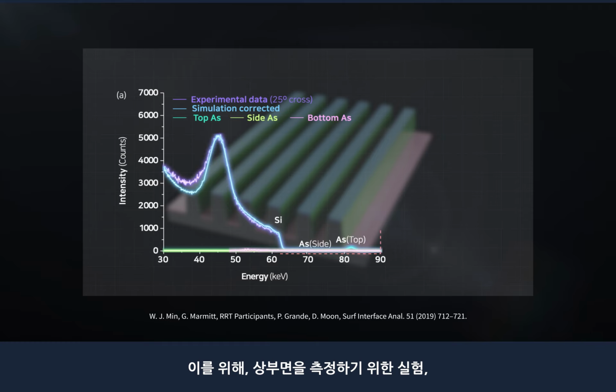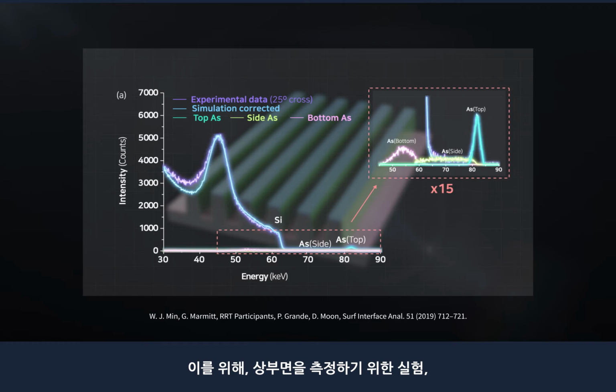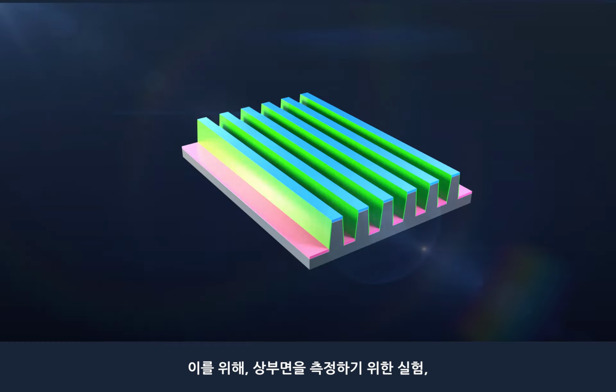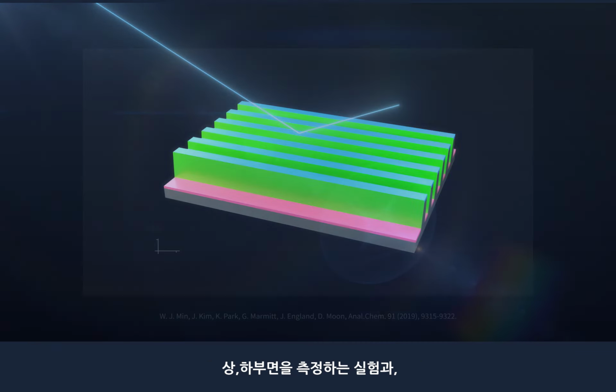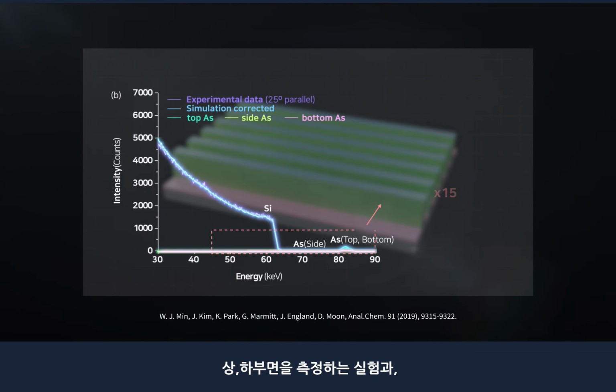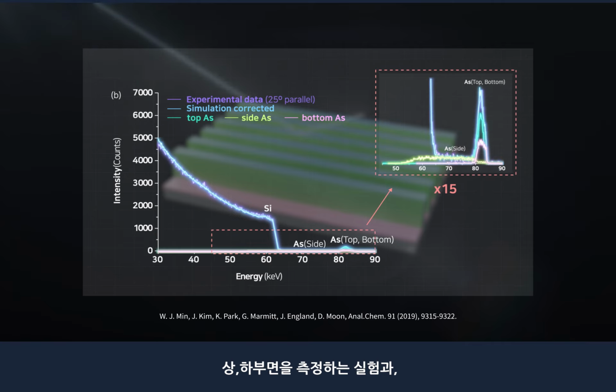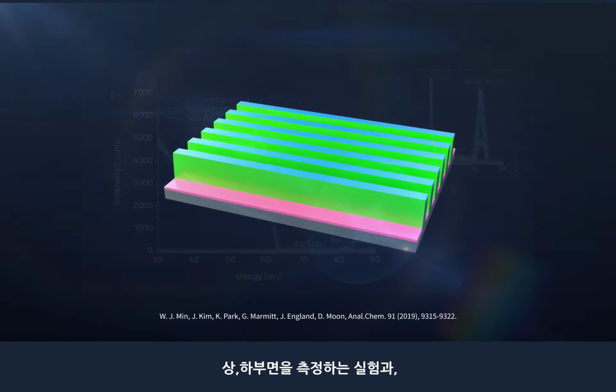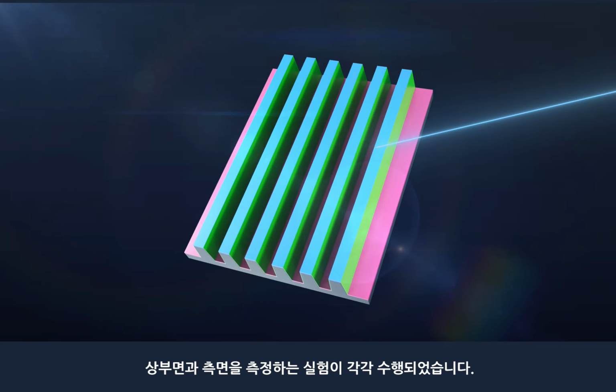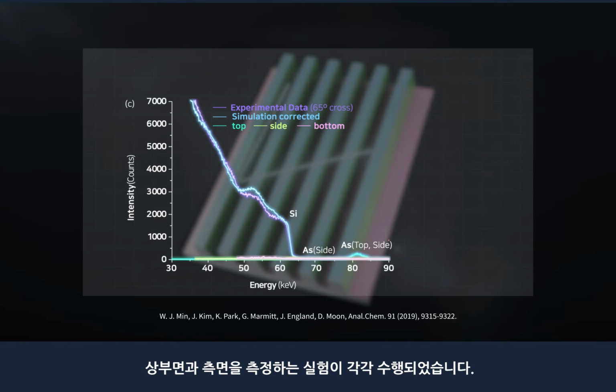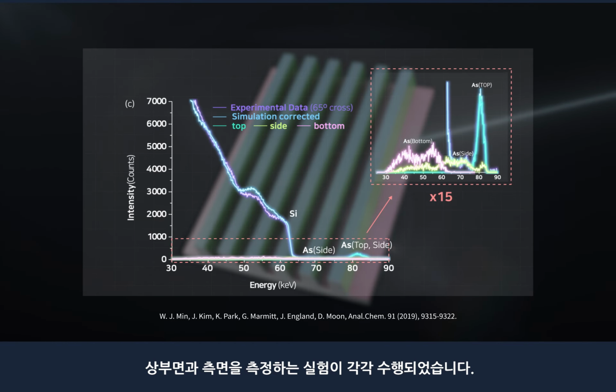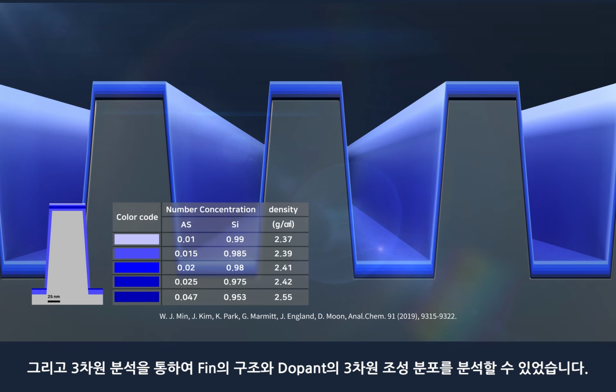An experiment to measure the upper surface, an experiment to measure the upper and lower surfaces, and an experiment to measure the upper and the side surfaces were performed. Consequently, the structure of the fin and the 3D composition distribution of the dopant were analyzed through 3D analysis.